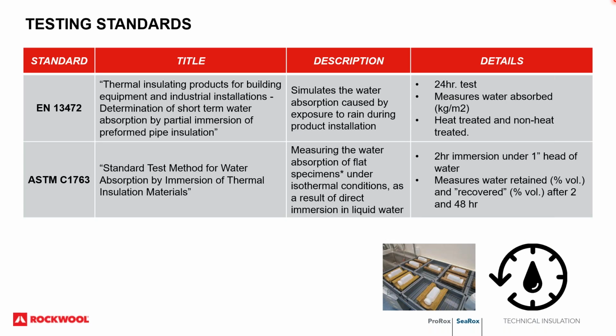So what tests? Corrosion is directly related to the time of wetness. Less water and faster dry out equal less corrosion. The ASTM G189 testing and results presented in the previous slides looked at the drying out time part of the equation. The other part of the equation we wanted to investigate was the time of wetness, and we used the EN 13472 test and the ASTM C1763 test.